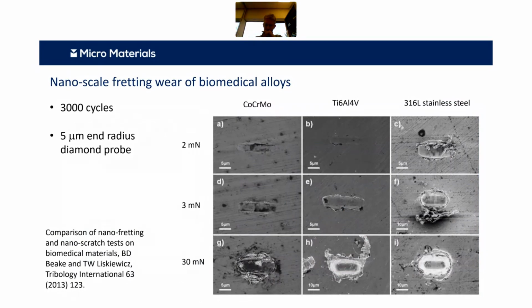So the work we did in conjunction with Tom Liskiewicz quite a while ago now was looking at small-scale fretting of alloys, and there we were able to correlate with things like the H/E ratio in the material, and then looking at different load levels. And we could see in this example that the titanium 6-4 particularly does well at the lowest forces.